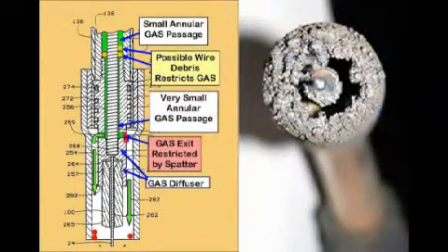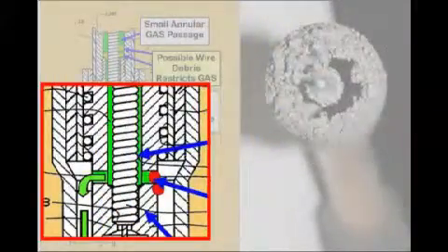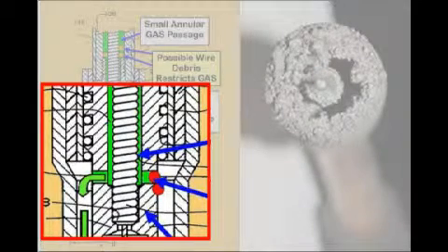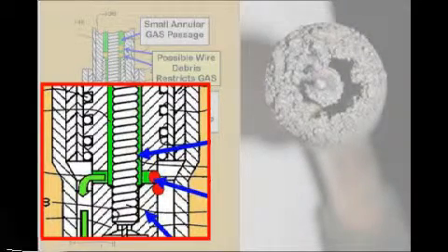What causes flow restrictions when welding? When spatter builds in the nozzle and when small gas passages in the gas diffuser clog with spatter, increased flow restrictions exist. Also, the small gas passages in the gun and gun cable, which often doubles as the wire conduit, become partially clogged with copper flakes and wire drawing lubricant.